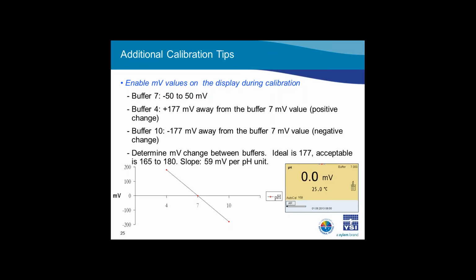In buffer 4, we are looking for a positive change in the millivolt value of 165 to 180, with 177 being the ideal. In buffer 10, we are looking for a negative change in the millivolt value of 165 to 180. For example, if we get a millivolt value of -10 in buffer 7, we would expect a millivolt value of 167 in buffer 4 and -187 in buffer 10. Most modern instruments store these values as part of a calibration record so it can be reviewed later. We will discuss the calibration record in a few minutes.